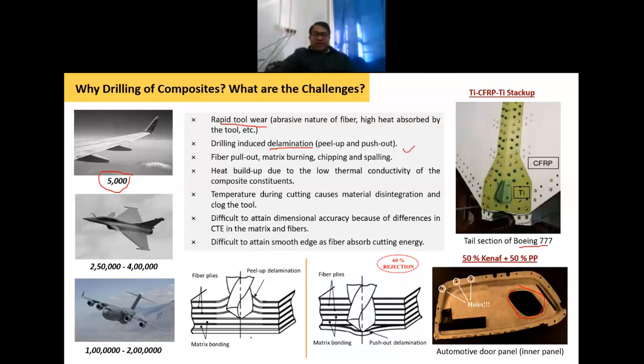So here you can see this is a peel up type delamination and this is a push out type delamination. In both types of delamination, you will see the separation of the layers. Peel up you will observe at the entry side of the hole, when the drill bit is entering into the laminate, and push out you will see at the exit side of the hole, that is when the drill bit is coming out from the other side of the composite laminate. In both cases you have the separation of the fiber layers, and this is called delamination.